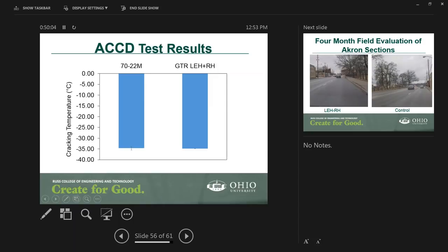What is interesting now, the cracking temperature for the GTR mix was actually slightly colder as compared to the 70-22. Not much, but there is about half a degree difference. So it's, again, an indication that there might not be differences in terms of the cracking temperature between both.